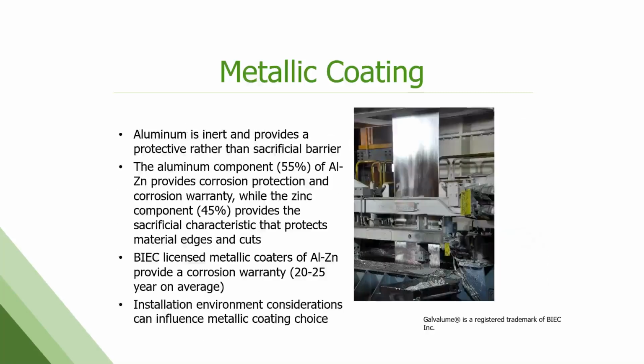And it's inert. The aluminum is inert. The zinc is sacrificial. So the Galvalume product is a licensed product, as is the Zincalume product. If you're calling your product Galvalume or Zincalume, you have to have a license from an organization called the BIEC. Almost all license holders are providing 20 to 25-year corrosion warranties on the substrate for this product, so that separates it from galvanized and some other coated metals that are out there, and then it has a warranty to back it up.